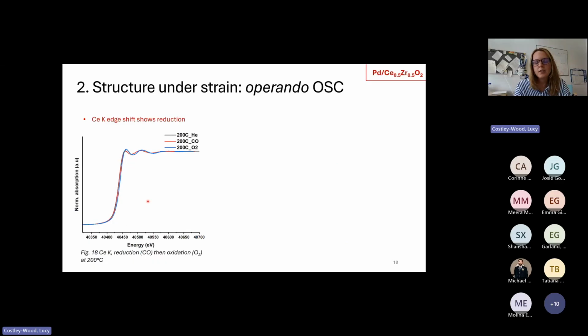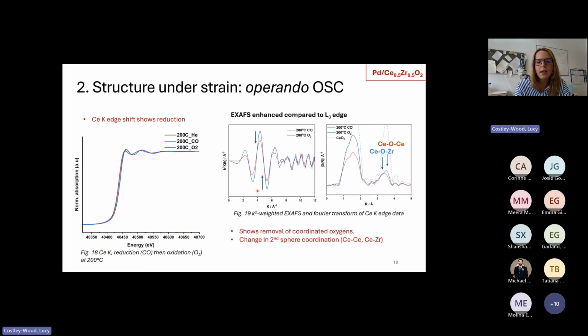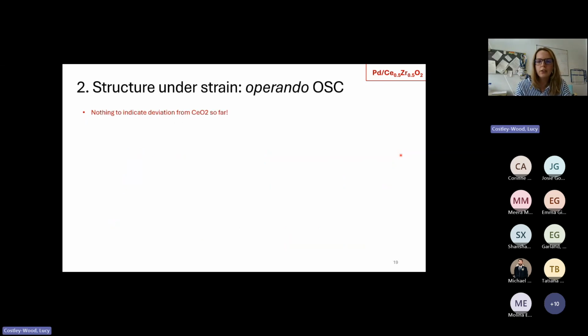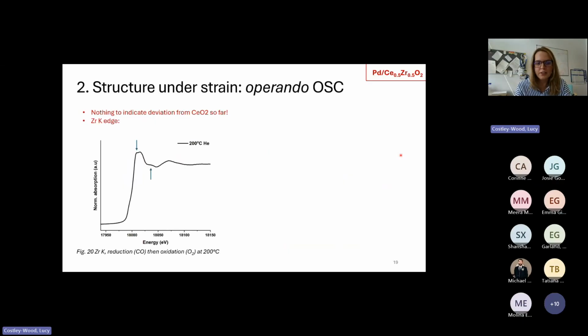Looking at the cerium K-edge, the XANES doesn't tell us too much other than that a reduction is occurring, but looking at the EXAFS, we now see this decrease in amplitude here, which tells us that we're losing oxygens from the first coordination sphere. And we also see some changes going on in the Fourier transform for the second shell, which I'll explain in a minute, but we're looking into a bit more. But so far, none of this seems to indicate a deviation from pure ceria. We have a cubic material that is not changing symmetry, is just losing oxygen and then regaining it, until we get to the zirconium K-edge.